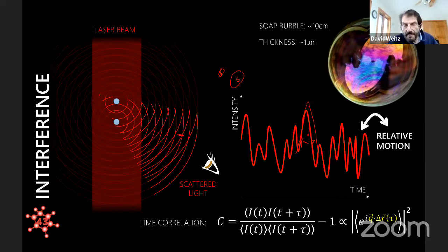And so the way you determine what's happening is you don't try to measure exactly what's happening here, but instead you calculate a correlation function for something that looks like this. You correlate the signal with itself. You can see I've written it down here. You would do a time correlation, and something like this will have an exponential decay of the correlation function. That's just showing the motion of one particle relative to another, but it's coming about because you're looking at the behavior of a single speckle.